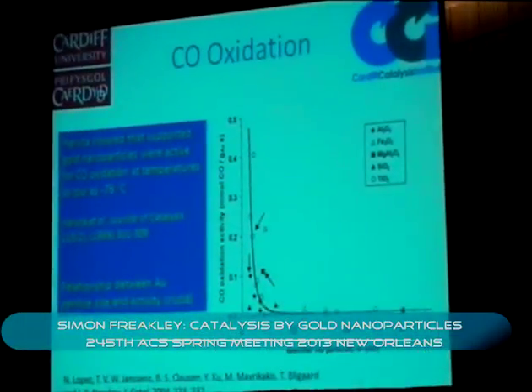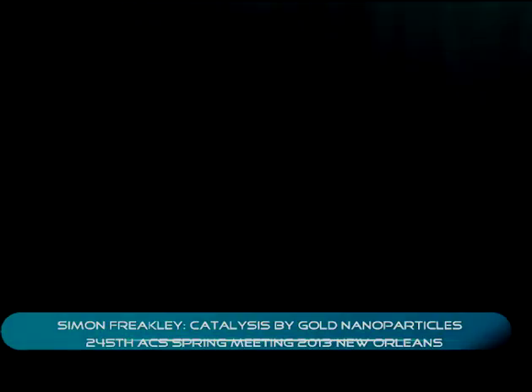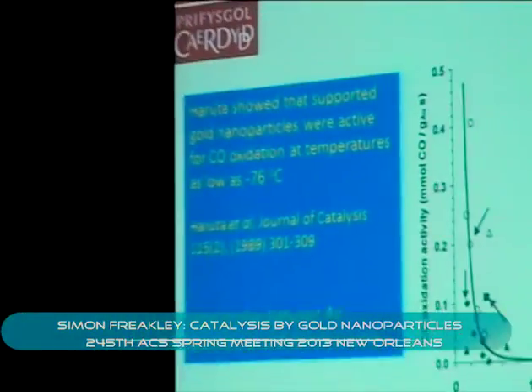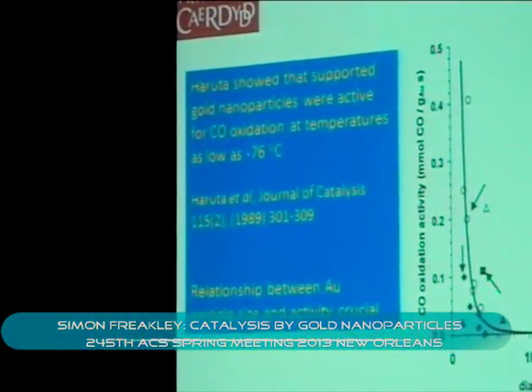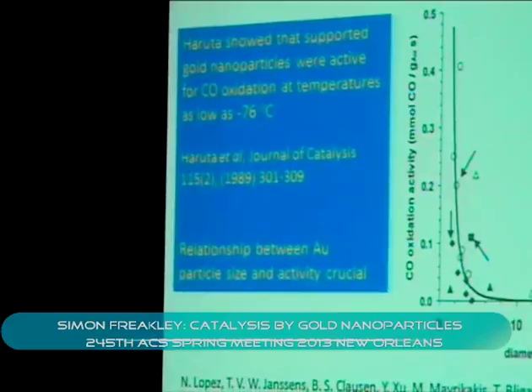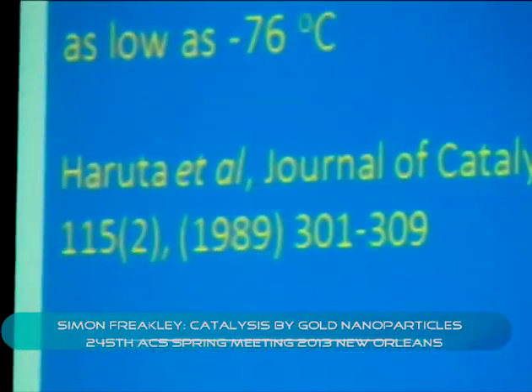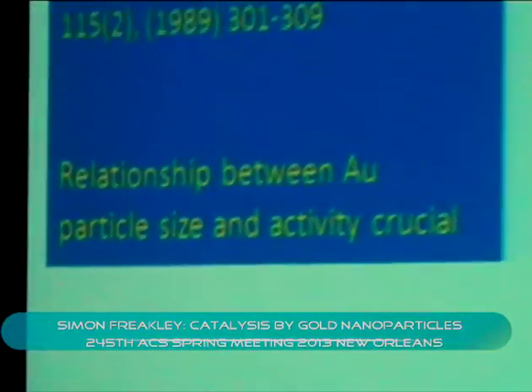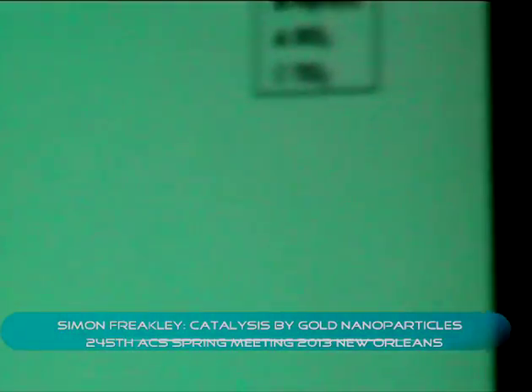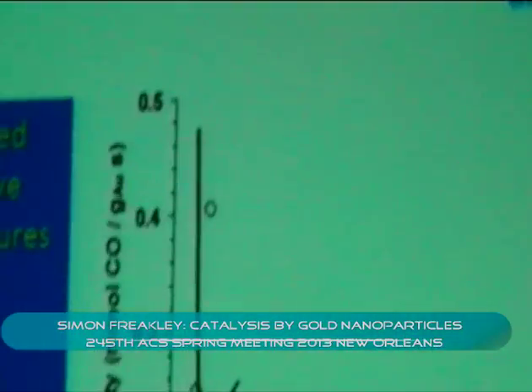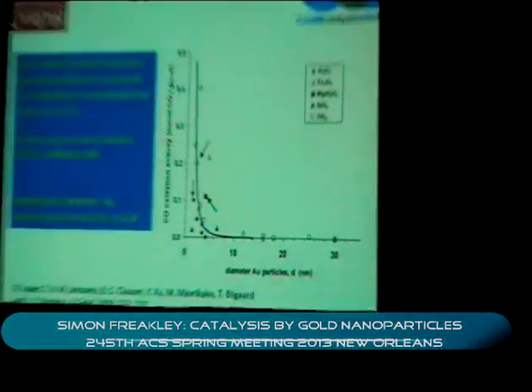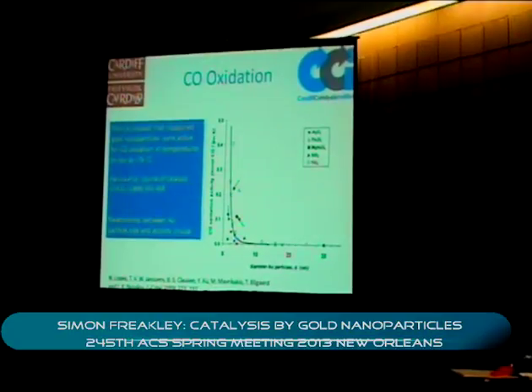So in 1989, while studying composite oxides for combustion catalysts, Professor Haruta discovered that gold nanoparticles could be active for CO oxidation at temperatures as low as minus 76 degrees C. Through data subsequently combined in the literature, it was shown that a relationship existed between gold particle size and the activity, where small gold particles were needed for high activity, which was almost independent of the support used. We always needed a small gold particle for high activity.